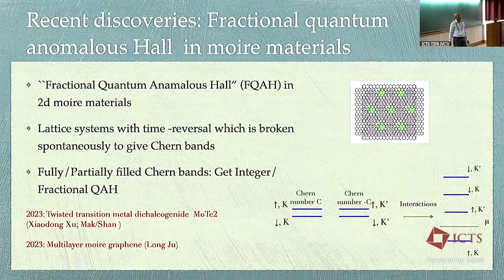In these Moiré systems, the electrons live in two different valleys, and these two valleys are related to each other by time reversal, right? So, for instance, there's one valley that's labeled by K. There's another valley labeled by K prime, and these two are related by time reversal. And you may have spin as a live degree of freedom, and so then you have two bands in each valley. Since time reversal acts by taking one valley to the opposite valley, within a single valley there is no time reversal invariance. So the bands can have a Chern number within a single valley, so long as the bands in the opposite valley have the opposite Chern number, right? So this is the situation microscopically.